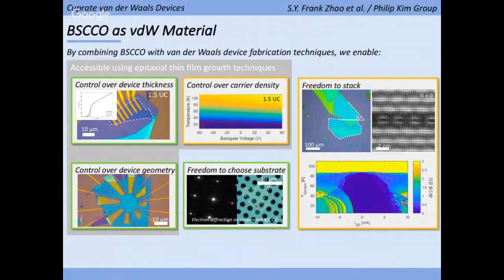So, yeah, naively, we were hoping to see something like that. I don't think we see that yet. We're still working through the data. One problem is that these things tend to be a little bit sensitive in that you have to put the flake down within about 2 minutes of exfoliating. So they're not always reproducible. But what seems to be maybe true, it's not quite sure, is that the superconducting critical current seems to increase with temperature when the flakes are angled. And we're not quite sure why that is just yet.